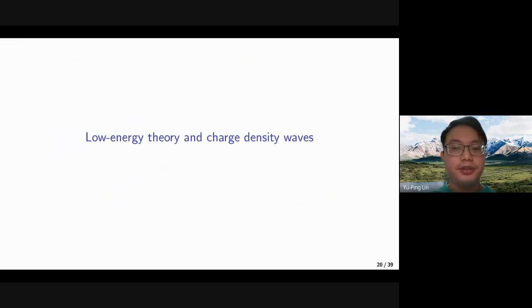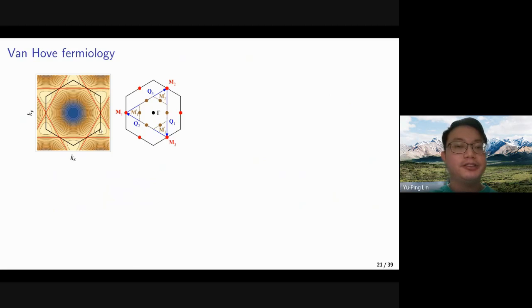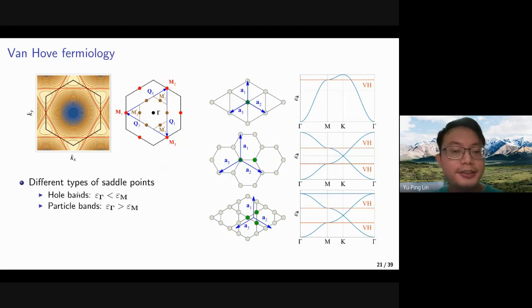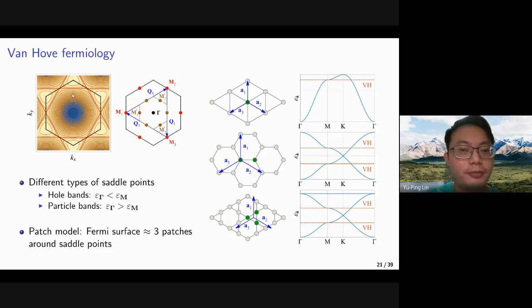So let me now address the low energy theory of the Van Hove fermiology. We should remind ourselves of the hexagonal Fermi surface in the hexagonal Brillouin zone. And there are saddle points at the zone edge centers, which are related by Qs. The first thing to notice is that we have different types of saddle points. The first type is on the hole bands, where the gamma points are lower than the saddle points, which occur on the triangular lattice, the honeycomb lattice, and the kagome lattice. And the second case is the particle band, where the gamma point has a higher energy than the saddle point, which occur on the honeycomb lattice and also the kagome lattice. For this kind of fermiology, we know that the Van Hove singularity occur at the saddle points. So we could approximate the Fermi surface by 3 patches at the saddle points. This is the low energy theory that we're going to adopt.